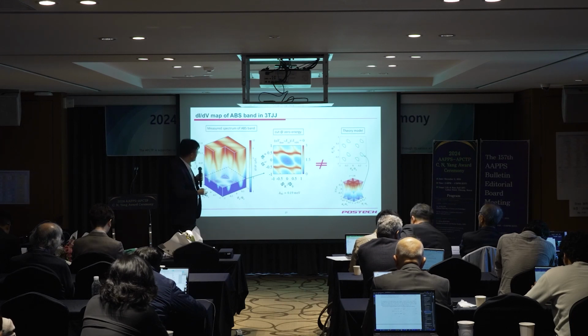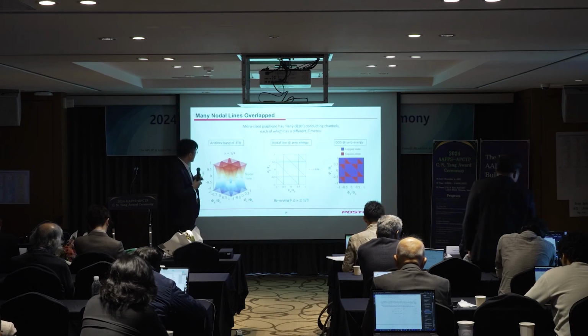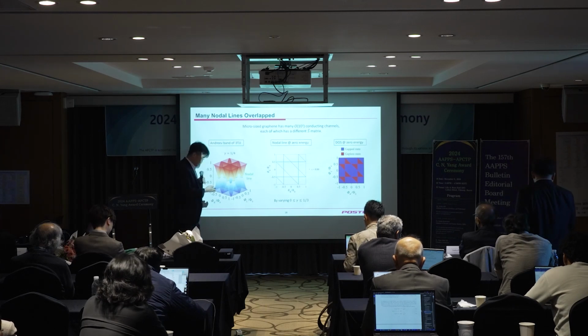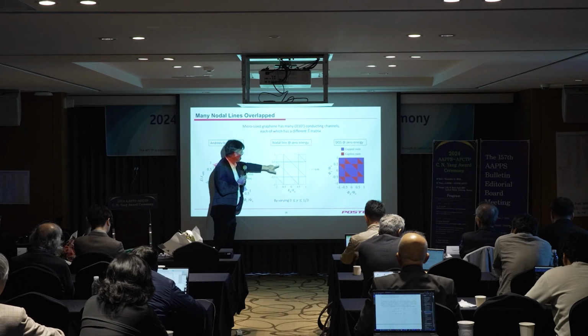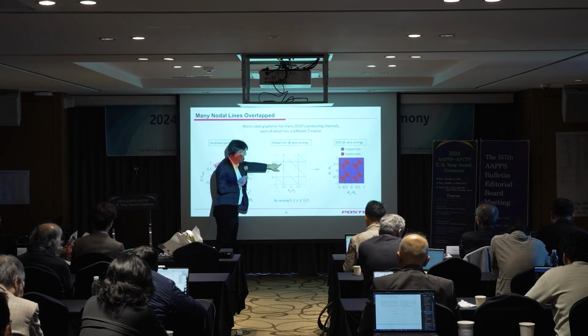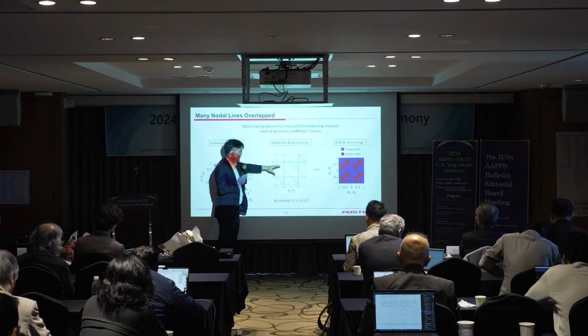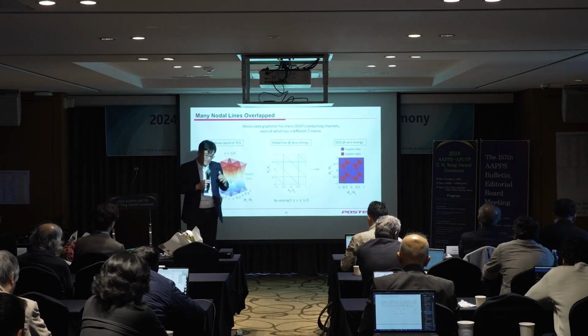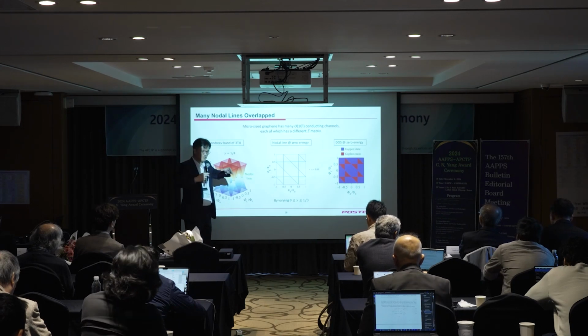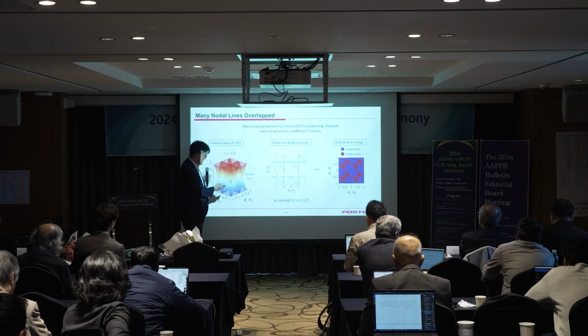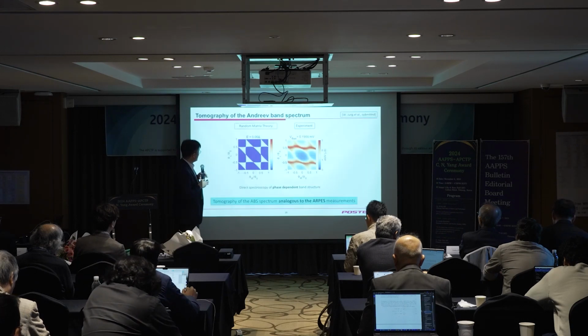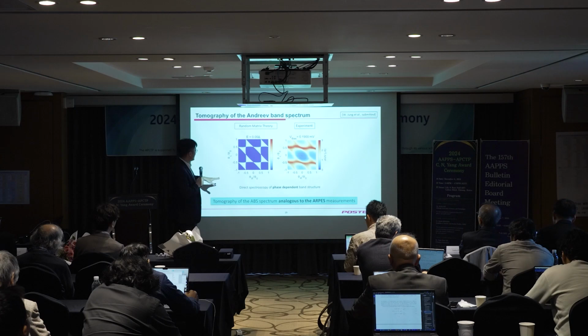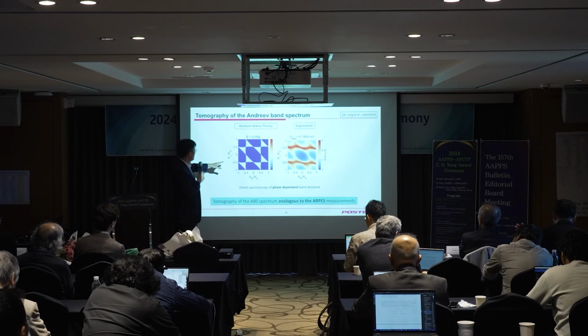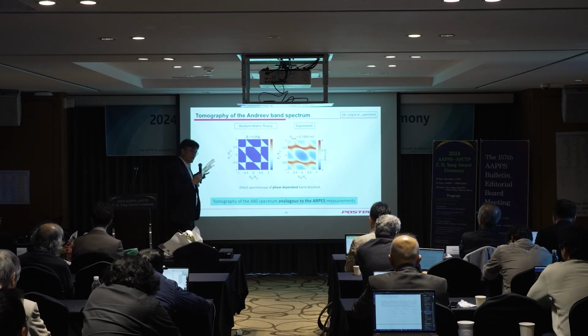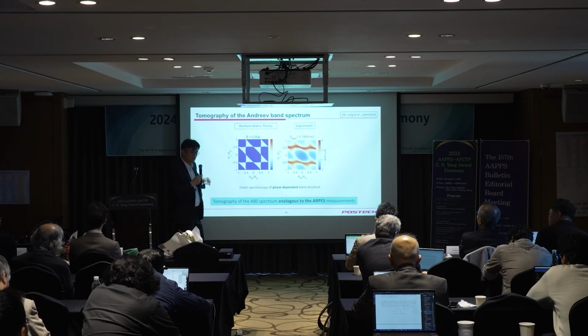So that's why. In the real situation, depending on the gamma value, you have different sizes of the ring. Because your system has all different possible scattering matrices, all these rings merged together make a plane of color. Anyway, this is a bit of detail. I wanted to show the energy-dependent cut at different energies, but basically I want to say that this random matrix theory can well explain the experimental data we've measured.